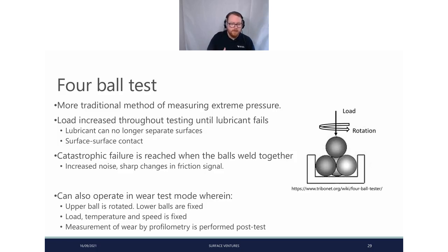For an extreme pressure failure test, the load is continually increased throughout the test. And this can help tell you when, once the lubricant is squeezed out, then you know the pressure at which it will no longer function. Once you have surface-to-surface contact, you can get cold welding, which of course, as Felix mentioned earlier, you can get this in fretting as well.